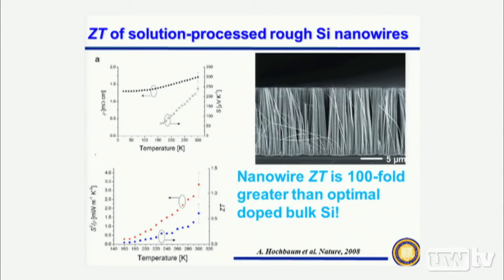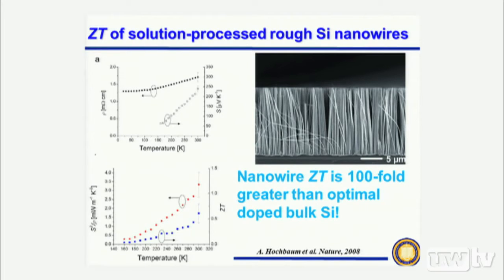So beyond the size-dependent properties of thermal conductivity, we further incorporate the surface roughness on these silicon nanostructures to further suppress the thermal transport. And that leads to a very simple process of producing nanostructured silicon materials that give you a ZT value 100 times larger than the bulk silicon. Okay? So ZT value for these silicon nanostructures now, we are getting close to 0.5, 0.6, and the processing is very, very simple. And that basically enables us to start thinking about really utilizing silicon to do thermoelectric power cogeneration. As now, finally, by nanostructuring silicon, we can develop better thermoelectrics.